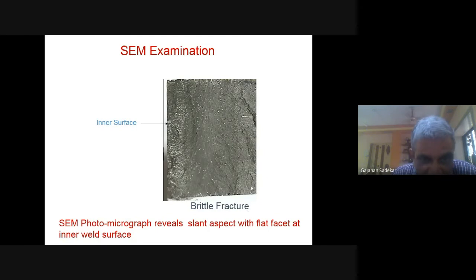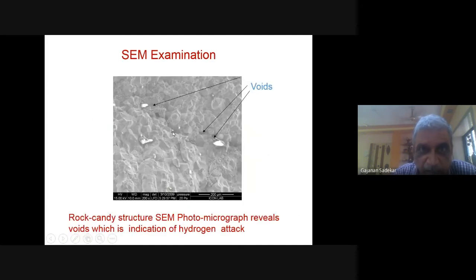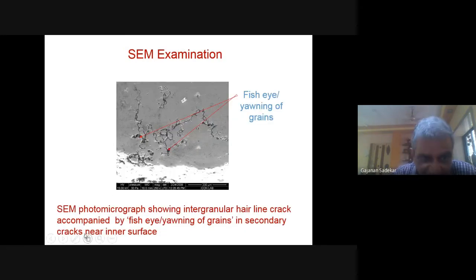If you look at these photographs, they reveal a slant surface aspect with a flat facet at the inner weld surface. This is what it means. Okay. Then rock-candy structure, and at photomicroscope level it reveals voids. Can you see these voids? There are voids which indicate that a hydrogen attack has occurred on the material. Then these photographs show the intergranular hairline crack accompanied by fish eye/yawning. This is called the fish eye/yawning. Okay. Grains in secondary cracks near the inner surface. So all these observations are very important.